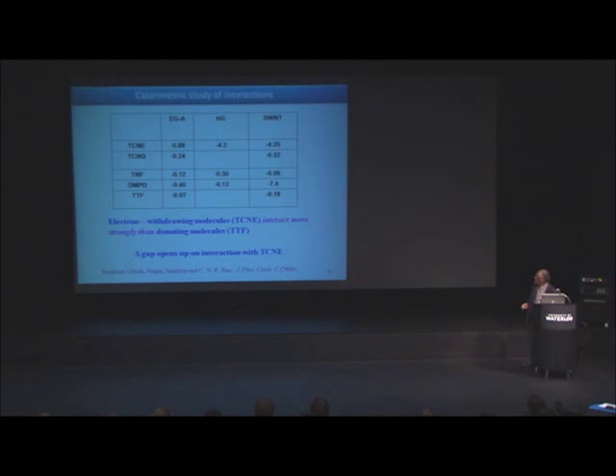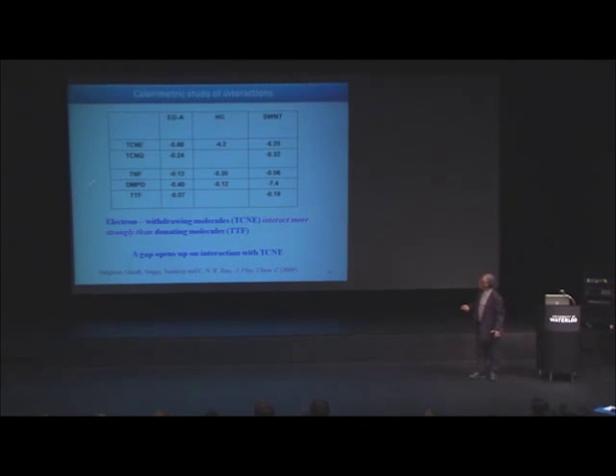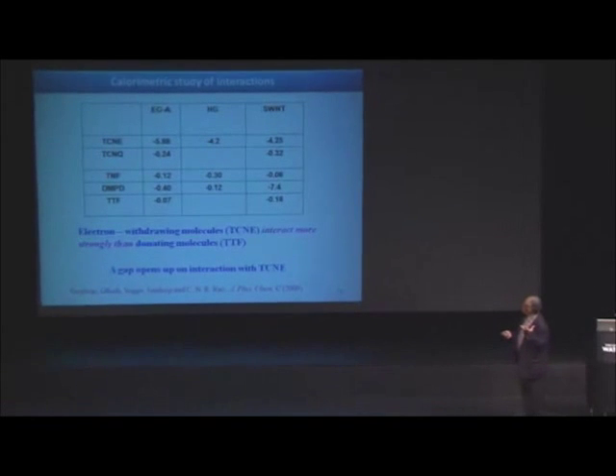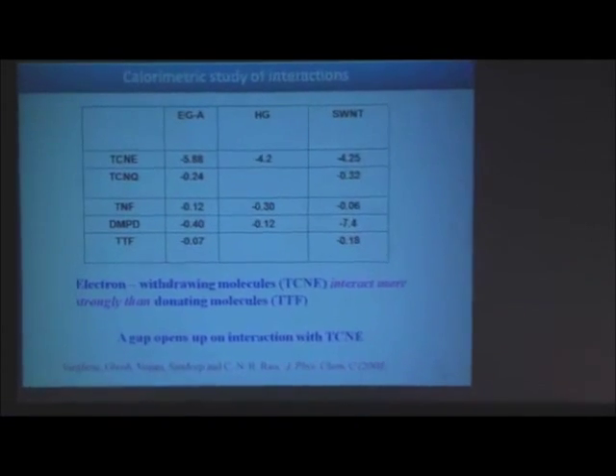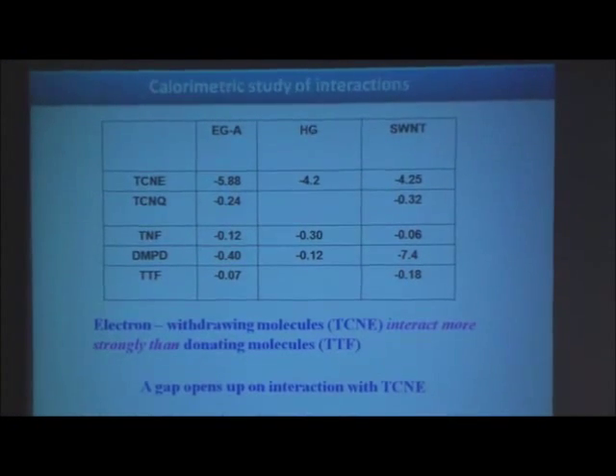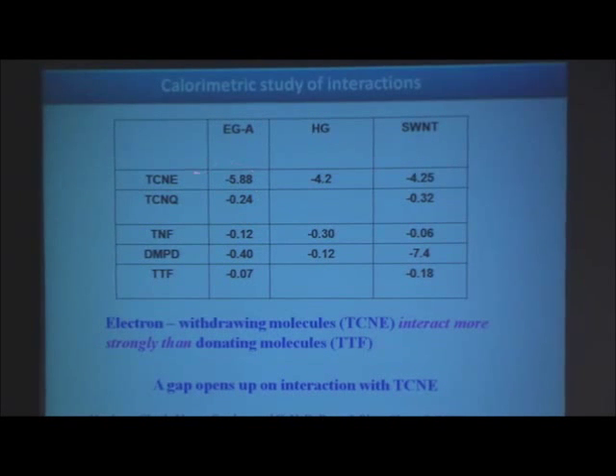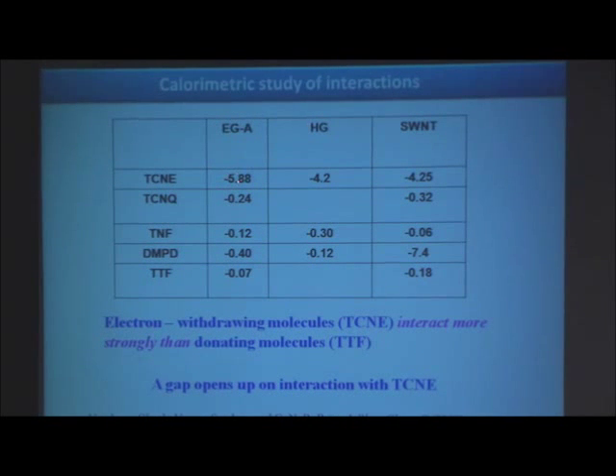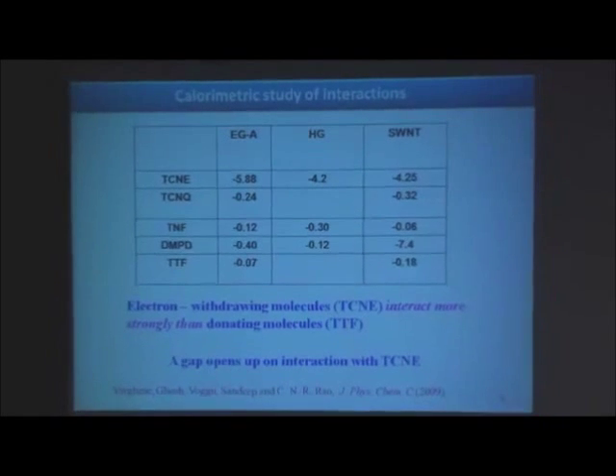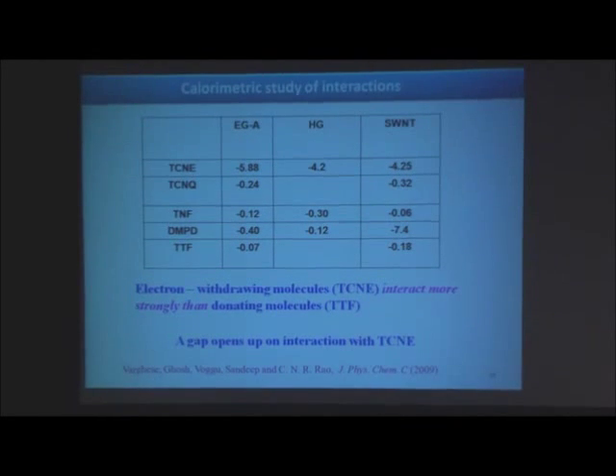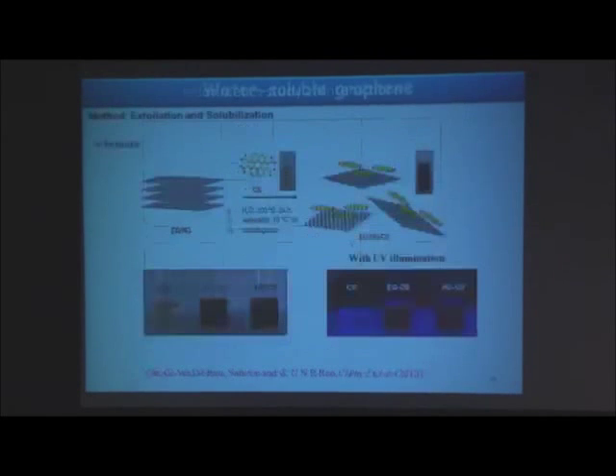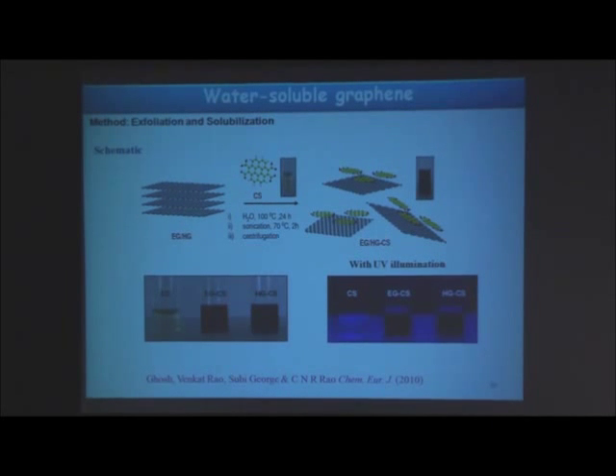You put a little bit of molecule on this, the 2D band intensity varies markedly, and we have studied all these effects. And since then, one of my students has also measured the interaction of these molecules by calorimetry and found the heats of reaction. When we put TCNE, we find a very large heat of reaction, comparable to that with nanotubes and so on. So electron withdrawing groups seem to open up the gap and so on. I'll come back to this in a minute.